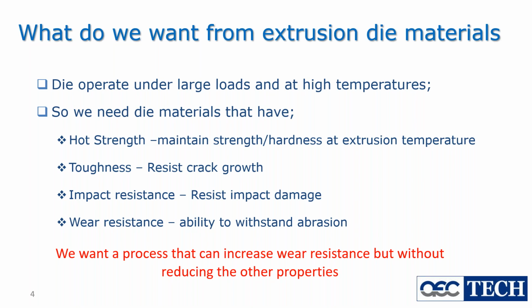Now, an extrusion die lives in a really quite aggressive environment. There is an enormous hydraulic machine pushing solid but hot aluminum through it. And the die operates under very high loads and at very high temperatures. And so that this works, the die steel has to have hot strength. It has to retain its hardness at extrusion temperature. There's no point in it going soft after a couple of hours at 1,000 degrees, because it's going to be spending most of its working life at those temperatures.